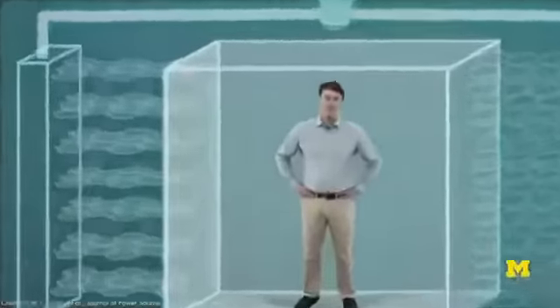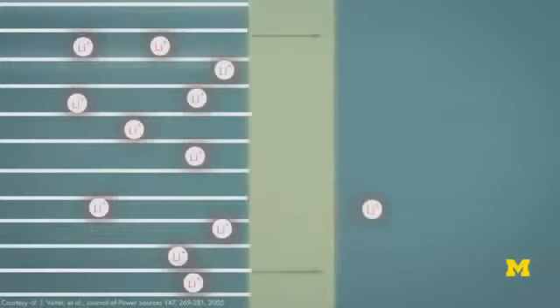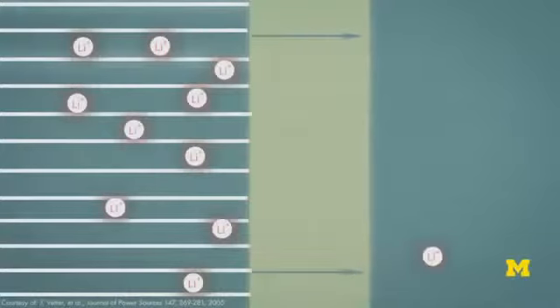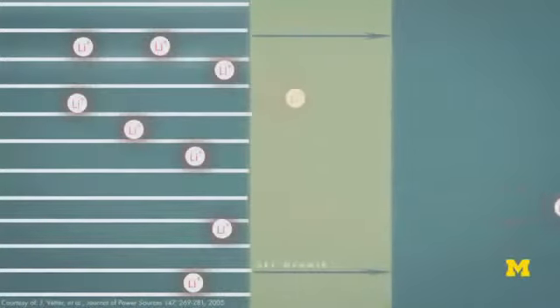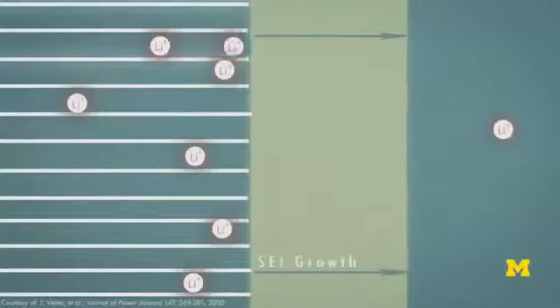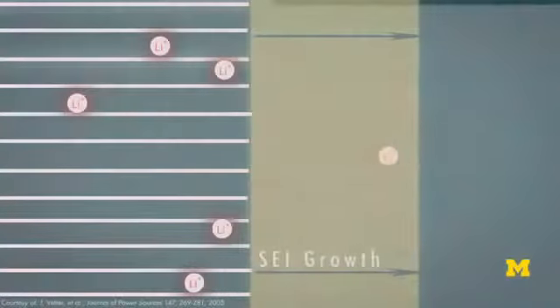The first one you can guesstimate just by noting that its formation arises from a reaction between the electrolyte and the anode. The SEI contains a fair amount of lithium, and lithium is an active material, so if it's tied up in the SEI, we're losing capacity. Also, we're essentially converting some of the liquid phase electrolyte into a solid phase, which means that it's not going to be useful for promoting ion transport between the anode and the cathode. And both of those effects can get worse as we increase the temperature. We tend to increase the rate of SEI formation at higher temperatures. The problem of power fade is also directly tied to the formation of the SEI. You can see that the SEI is getting a little bit thicker, and so as that thickness increases, the ability of lithium ions to easily migrate through the SEI goes down, and so we see a rise of internal impedance, which results in power fade.